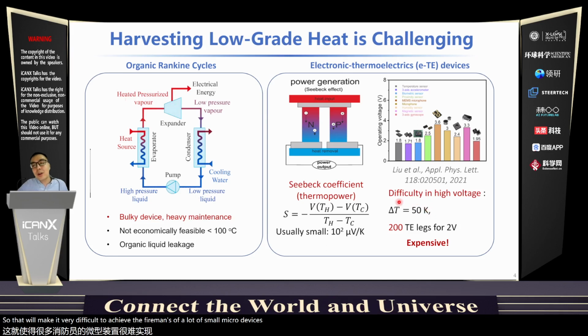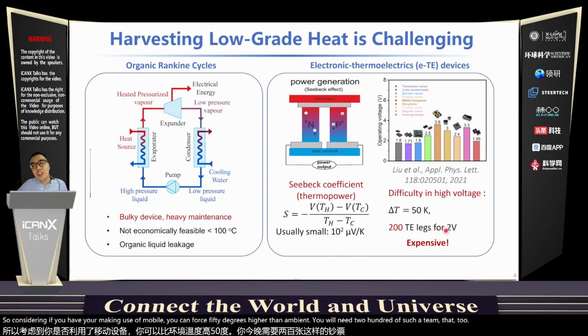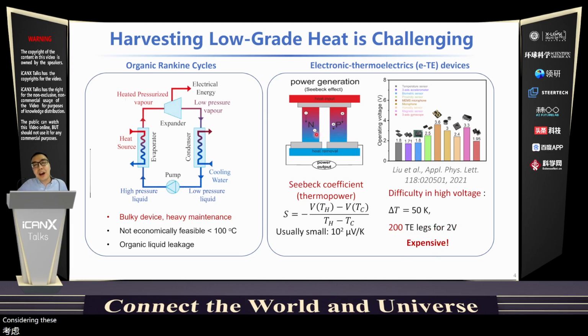Considering that if you're making use of a low-grade heat source, 50 degrees higher than ambient, you will need 200 of such thermoelectric legs to achieve a voltage of 2 volts. And that would be very expensive, considering these thermoelectric materials contain heavy and rare elements. So do we have a better option?